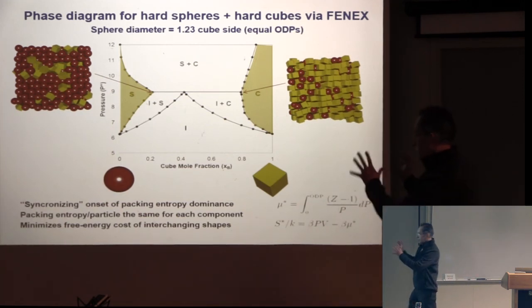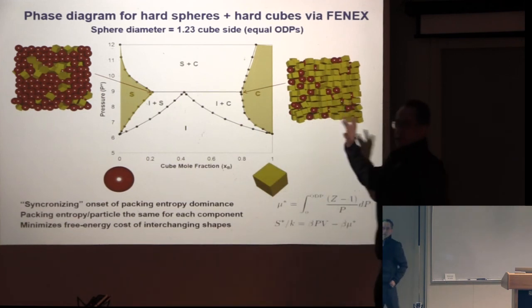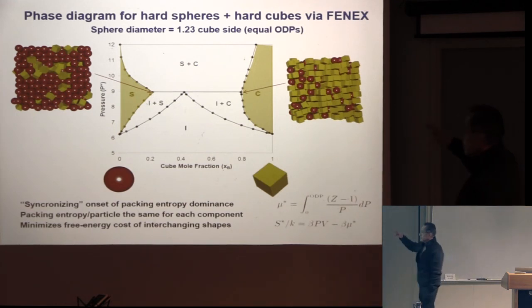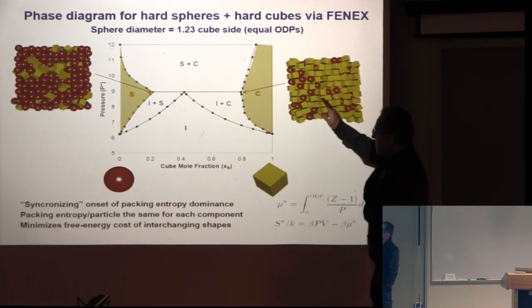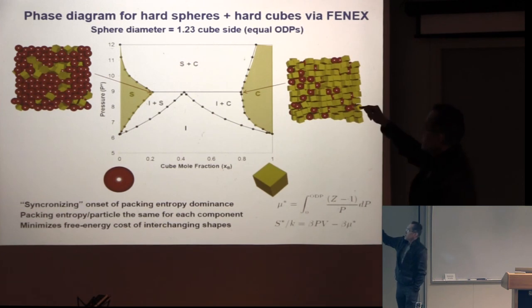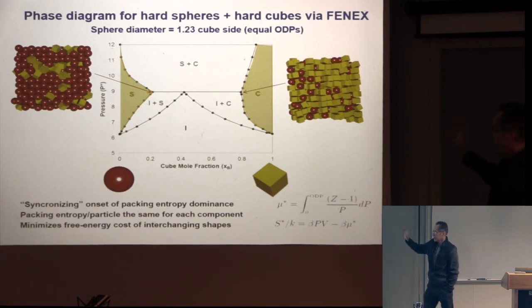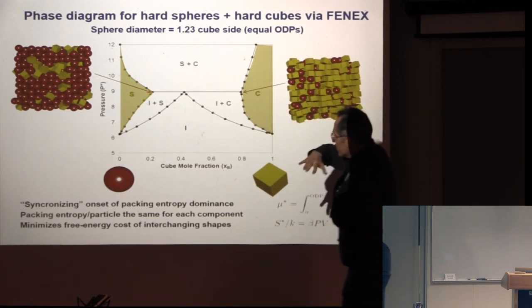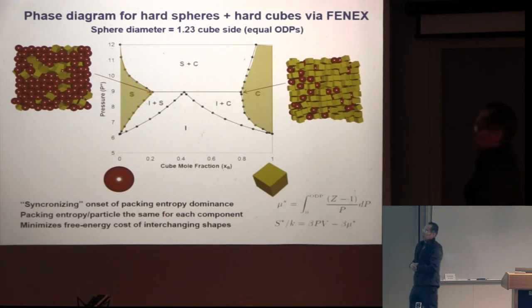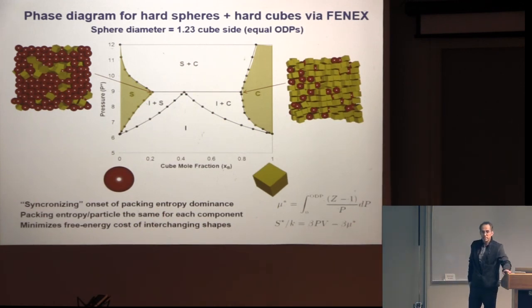Yeah, so I think that in this case, anyways, and I think that's true for any pair that you analyze, at the end, these entropy considerations are arising from the geometry, right? And you will find that there's something that makes sense as far as what the geometry should be. I should mention that that number is very forgiving, in the sense that you can be from 1.17 all the way to 1.3 and you almost get the same thing. So it's not like you have to be exact at that ratio. You have this broad plateau of ratios that will allow you to have this maximum solid phase miscibility. But I see your point that there is something about the geometry that maybe a priori can help you guide this calculation. You could allow local melting, right?